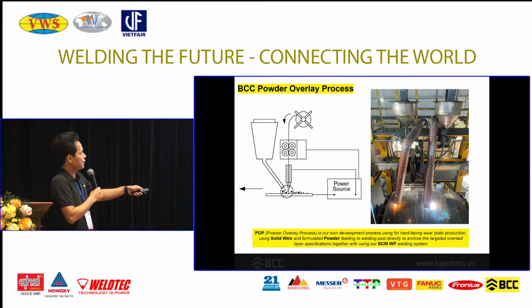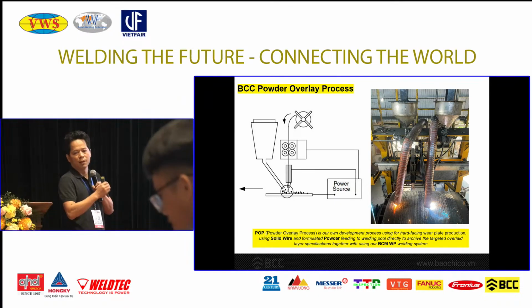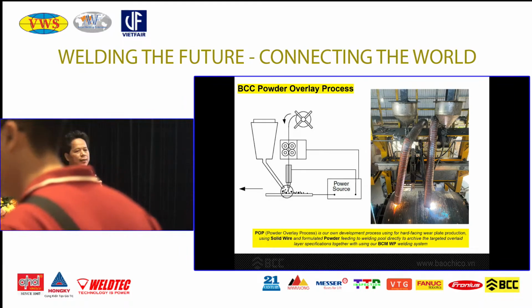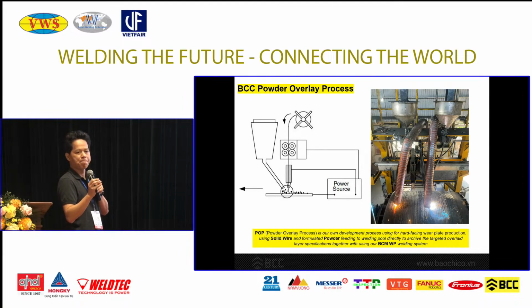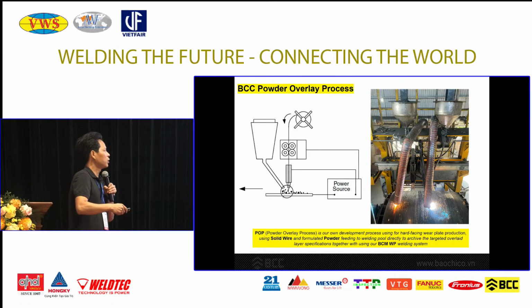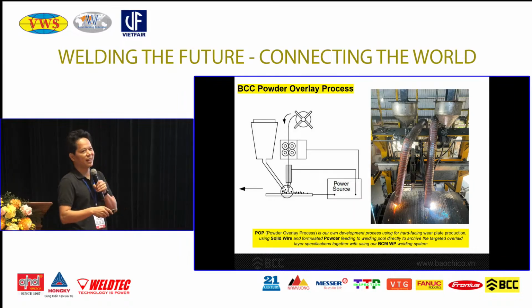You see here, this system was designed six years ago, and we had here the container supplying the powder to the welding pool. Here also supplying to the welding pool. Here the steel plate and the wire feeding. So we had to control how much wire we're feeding by controlling the wire feeding motors, the wire feeding speeds. And also we had a motor here to control the feeding speed of the powder into the welding pool. So this is something like submerged arc.